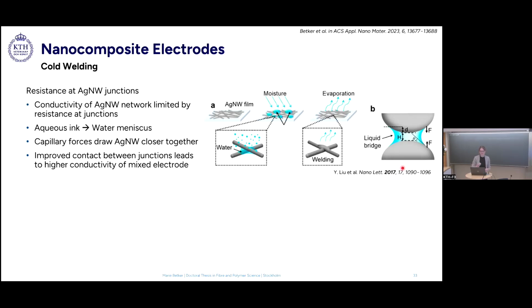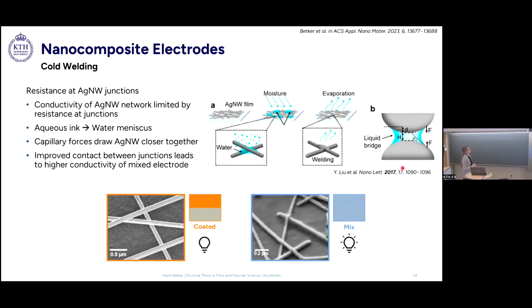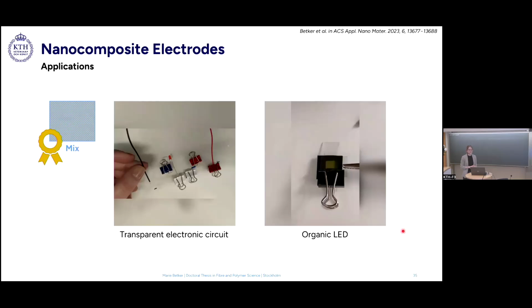And again, we compared it to different electrode types. We see here in orange, where we had isopropanol as the solvent, the nanowires are quite stiff, lying on top of each other, not really close together. In the mixed type, you can see how well attached they are to each other, which again explains why the mixed type is the winner here. So in summary, the mixed type is the winner here. And so I used it